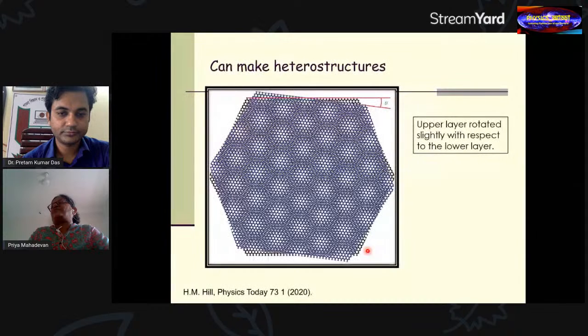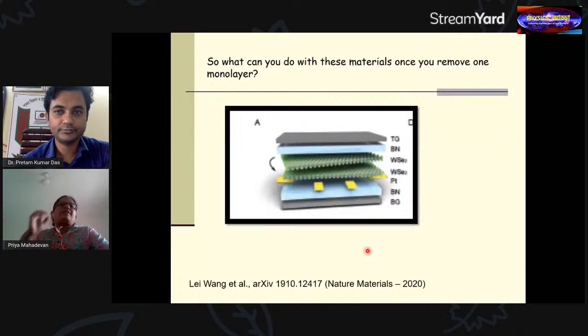And this actually depends on this angle by which I'm rotating the top layer and placing it on the lower layer. Okay. So now, basically, this was something which people did very recently, and it has appeared in Nature Materials, where they created a structure like this, where they took one of these transition metal dichalcogenides, tungsten diselenide, 2 layers of these, and created a structure of this sort.